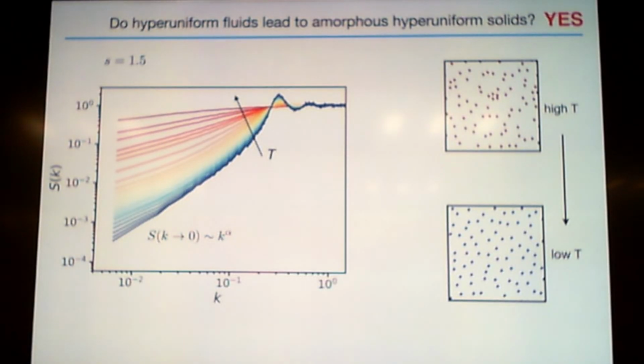There have been studies that showed that the glass has no difference at the 2-point level, but if you go to higher 3-point and 4-point correlations, you see some differences in glasses versus liquids. But even at the 2-point level, I think this is the first study that shows that there is a clear structural distinction between glass and liquid. Because the dominant idea is that glass is a frozen liquid. We believe it's not that simple in this specific category of systems.